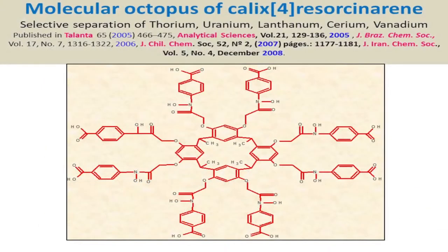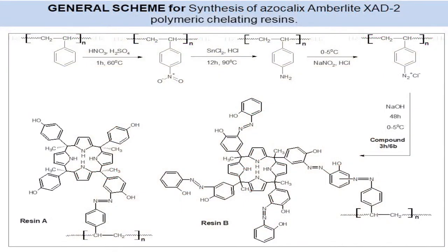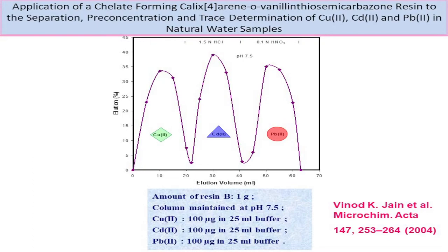This is a resorcinarene, which we have functionalized, octa-functionalization, and this we call a molecular octopus. It has been used for the selective separation of thorium, uranium, lanthanum, cerium, and vanadium. Likewise, we have taken the Amberlite XAD polymeric support, nitrated, reduced, diazotized, and hooked our calix system on these polymeric supports and used them for the separation and pre-concentration of various metal ions: copper, cadmium, lead, chromium, arsenic,